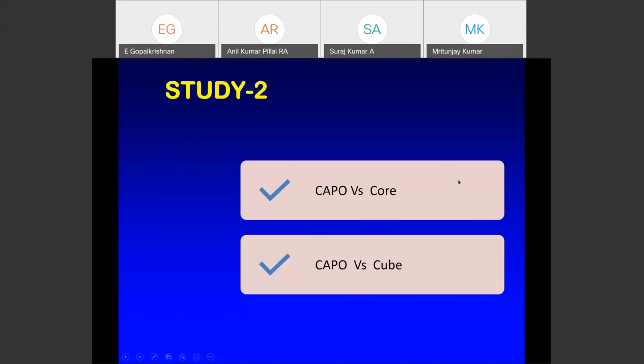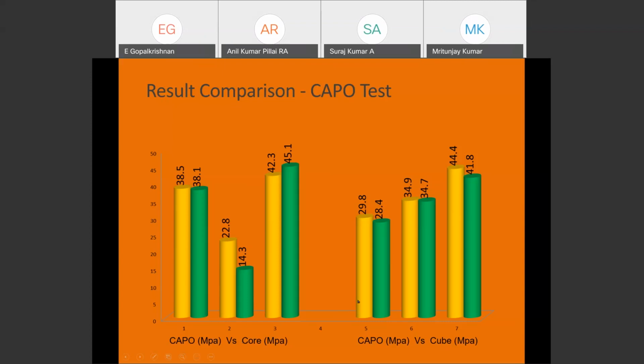Second, I did a comparison with the core as well as the cube. Wherever I did the CAPO test, adjacent to that I have taken the core, so that the compressive strength of the core should match with the CAPO, cut and pull-out test. I can see that mostly it's very, very close, except for one a little bit erratic result. So we avoid this result in the group, and you can see these two are very close. Similarly, when you compare the cube and the CAPO, also very close. All these come within 6% accuracy, whereas 8% is allowed as per the standard, so we are within the limit and giving more accurate results when comparing with the core as well as cube results.